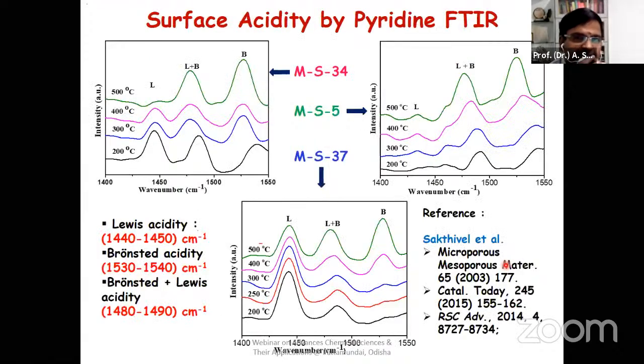Then, as I said, this material has acidity. How do we confirm the acidity? Normally the acidity can be confirmed through the pyridine adsorption method. Pyridine is a 5-member, sorry, I couldn't show the pyridine structure. Pyridine has aromaticity. When it is connected through the aluminum metal center, it forms Lewis acidic sites. And when pyridine forms the NH proton, that is a pyridinium proton, then it is called Bronsted acidity.